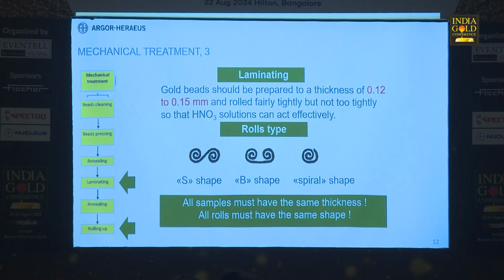Next step is the laminating. Laminating is another fundamental step, because the gold beads must be prepared to a thickness that is typically between 0.12 and 0.15 millimeters, and rolled up tightly, but not too tightly. Why this? Because we must let the acid enter in the rolls and do the parting, so they cannot be so tight. First of all, we must check the thickness of every single lamina with the gauge. This is because we must be sure that all the laminae have the same thickness, or at least we must guarantee that in an analytical series we have the same thickness for all the samples.